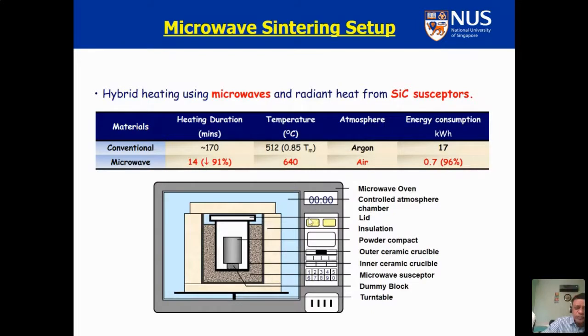So for example, to sinter magnesium-based material, we need 640 degrees centigrade. So we know that in 14 minutes, we can reach the temperature. So switch on the microwave, switch it off at 14 minutes. How much do you save on the time? 90%, because the same operation will take 170 minutes in a conventional setup. How much energy do you save? More than 90%. So basically it becomes a green process. And you get the material with similar or better properties than the conventional method.